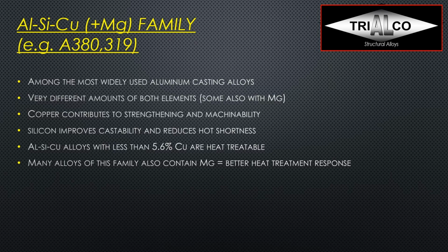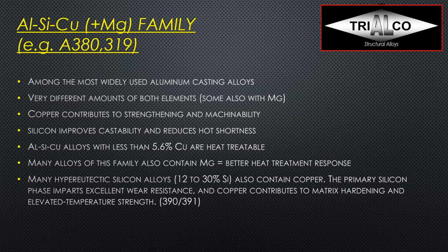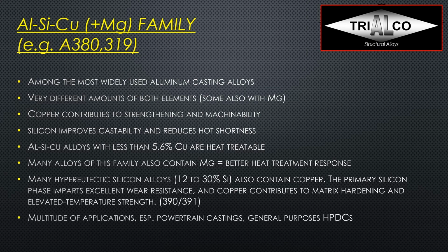There are many alloys of this family that also contain some magnesium, which will improve their heat treatment response, giving us the Mg2Si precipitation hardening, and many hyper-eutectic silicon alloys with 12 to 30% silicon. They also contain copper. The primary silicon phase imparts excellent wear resistance. We were able to see before in the microstructure, and the copper contributes to matrix hardening at elevated temperature. So we get high temperature strength combined with wear resistance. And that's what we see in the 390 or 391, for example. There are a multitude of applications, but a lot of them are precisely where we have exposure to high temperatures. So in powertrain castings and also, of course, many general purpose high pressure die castings.